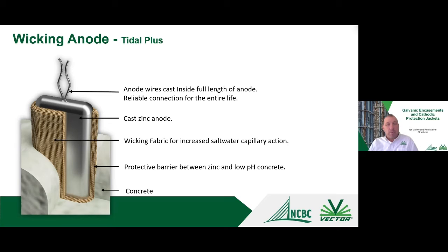And then if you remember back to the pH versus the corrosion rate chart, it's also going to act as a protective barrier between our lower pH of our concrete, which is roughly around 11, and our zinc. So we do not want our zinc to be in contact with the concrete within that jacket. And by doing that, it's going to allow the zinc to remain in a more active state and basically provide a higher level of cathodic protection for the jacket.